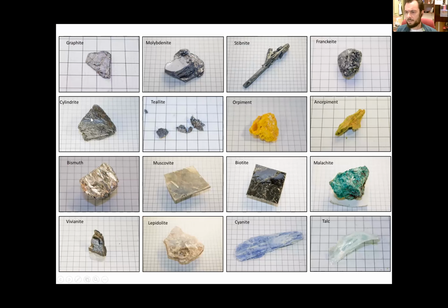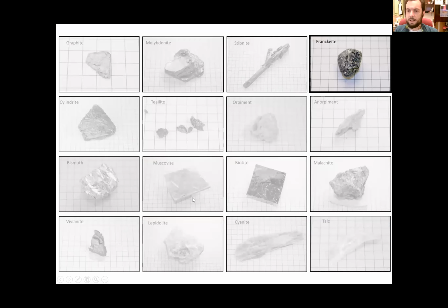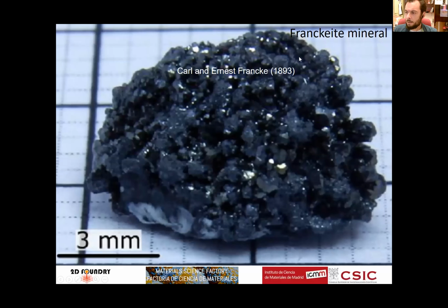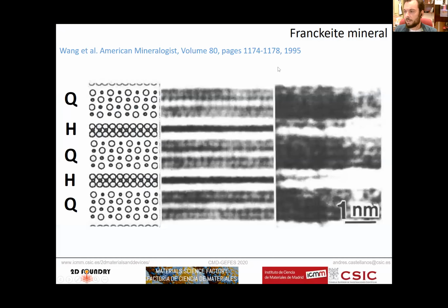Okay, so all these materials are layered compounds, and out of them we got interested in franckeite, because it's a relatively new mineral, but already from the 90s it was known that this mineral had a structural composition of alternating layers. So a pseudo-tetragonal layer, quasi-cubic let's say, then a pseudo-hexagonal layer, pseudo-tetragonal, pseudo-hexagonal, pseudo-tetragonal. So this kind of superlattice structure.